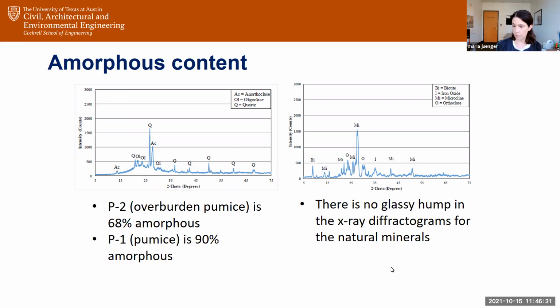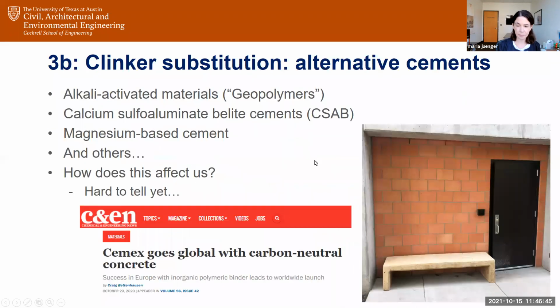So we have to be careful when looking at these data and looking at these materials to really make sure that all of our criteria are satisfied. They have to be amorphous or at least soluble, fine-grained, have silica and alumina, and they have to be reactive. So we have to be a little careful in our search as well. So that's my warning sign.